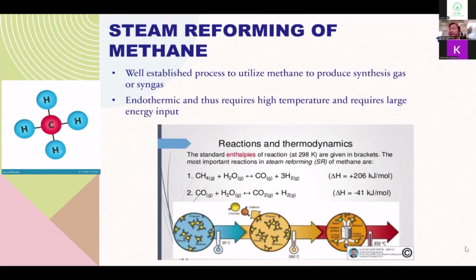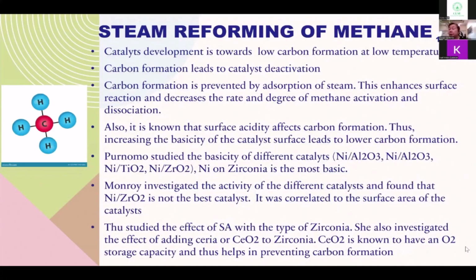Steam reforming of methane is a dominant commercial method suitable for hydrogen production and ammonia synthesis. The ratio of hydrogen to carbon monoxide in this case is rather high for methanol production and other products. So this process requires high operation temperature, leading to the deactivation of the catalyst and consuming a large amount of energy. Many researches have been conducted related to this problem in order to reduce energy consumption and lower the reaction temperature. The catalytic steam reforming of methane is a well-established process for converting natural gas into hydrogen or synthesis gas in industry. However, a large amount of energy is necessary because SRM is a highly endothermic reaction.